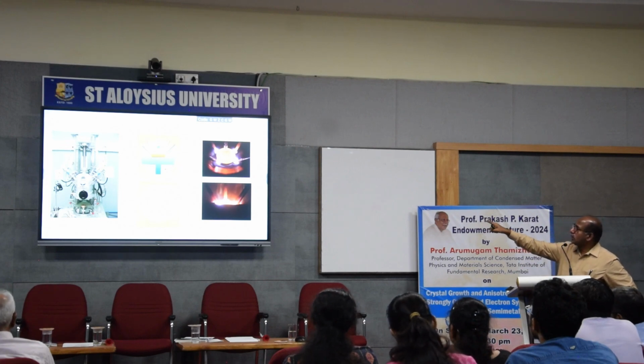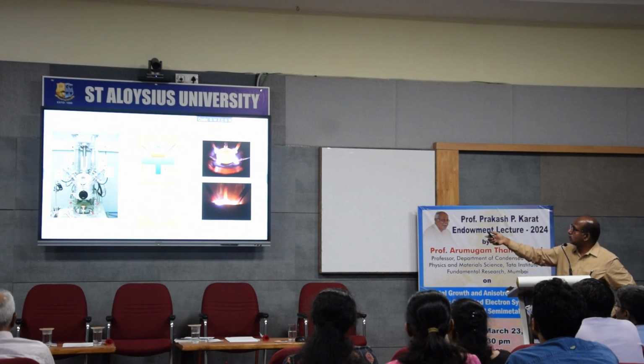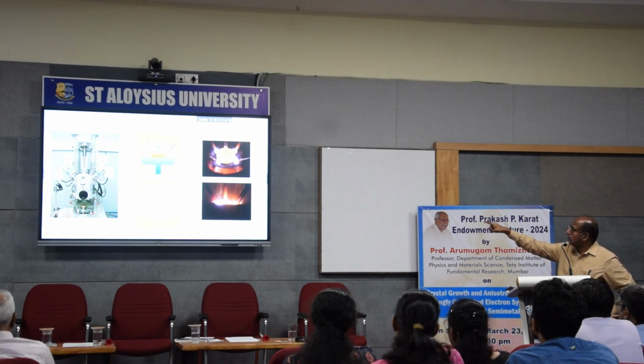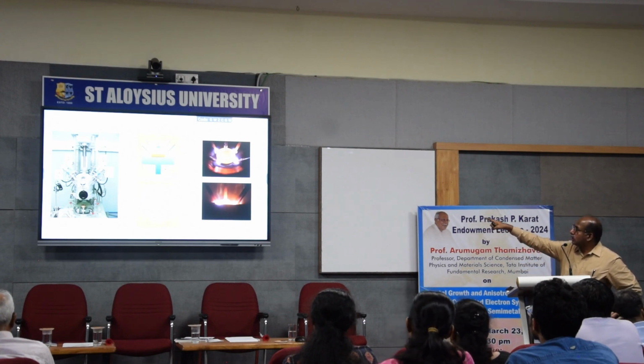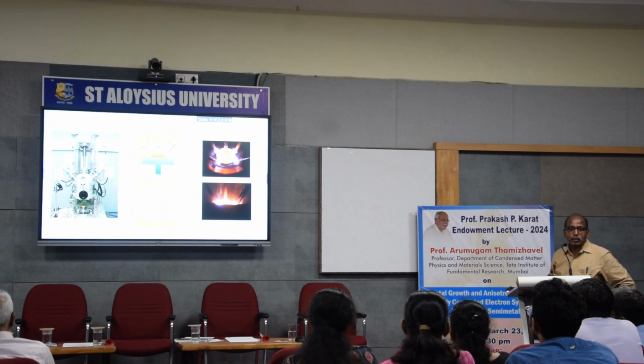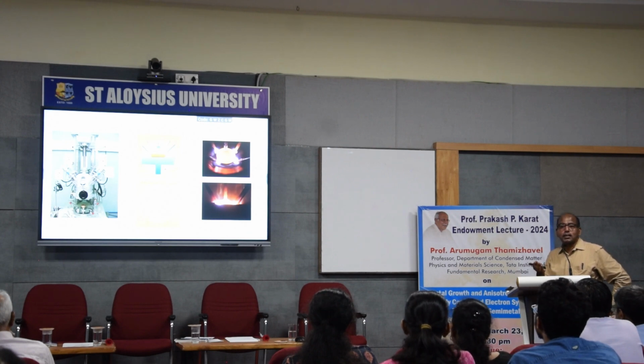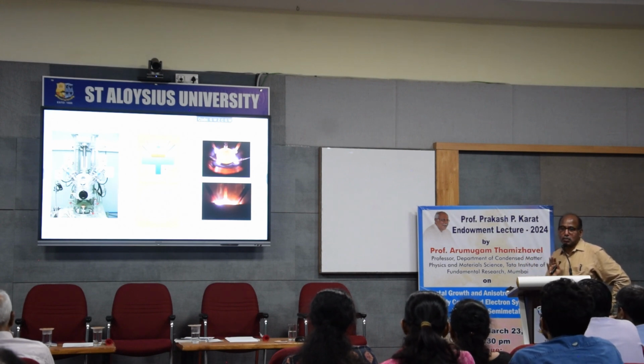You take the material in a hearth. This is called the copper hearth, the brown colored stuff. In the middle figure, the blue colored one is water cooled. The copper has a high thermal conductivity, but it melts at 1000 degrees centigrade. But I can hold a metal whose melting point is 3000 degrees centigrade in a copper hearth, because copper is highly conducting, the heat will be taken away by the water and the copper will not melt.